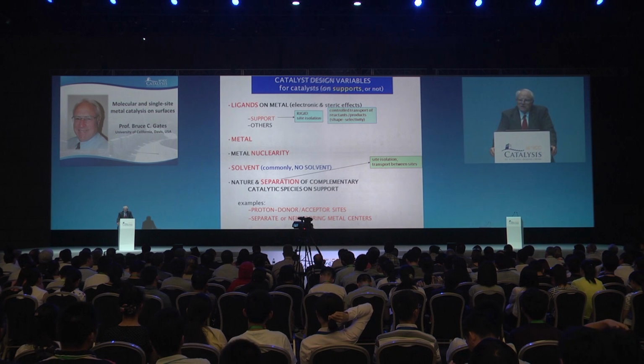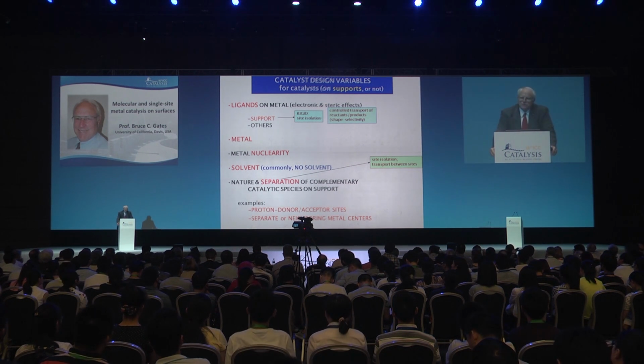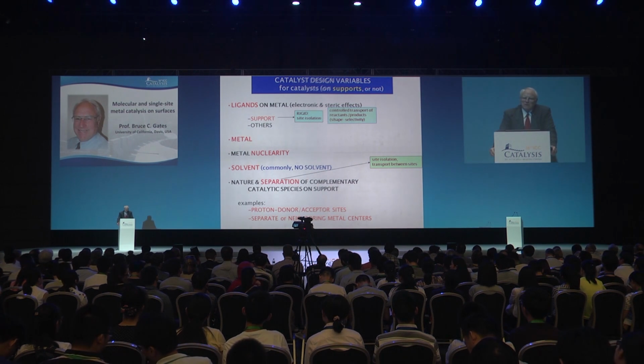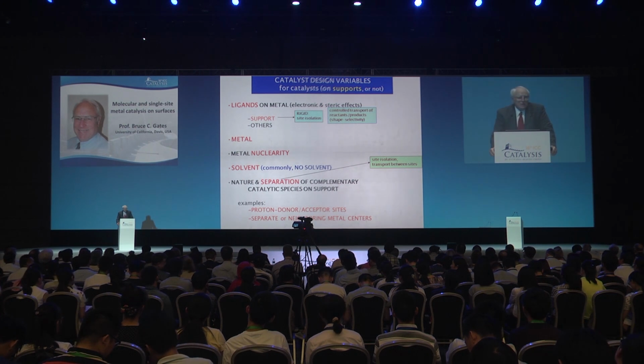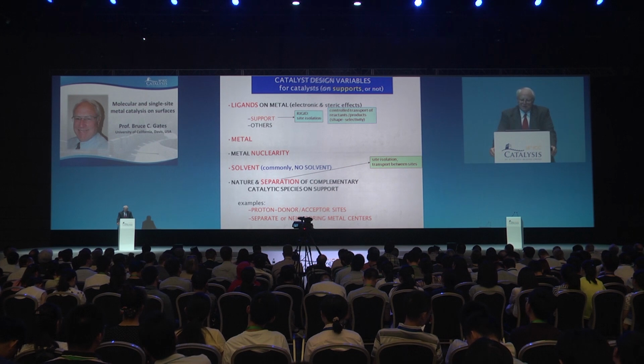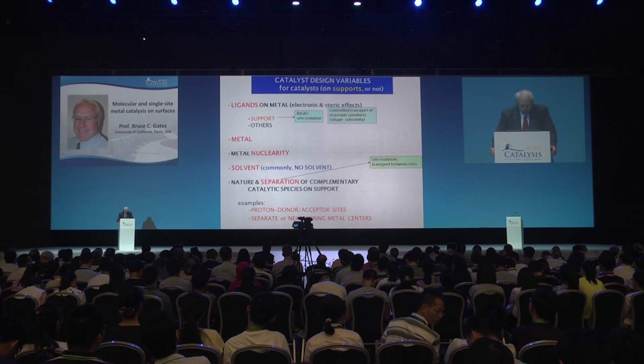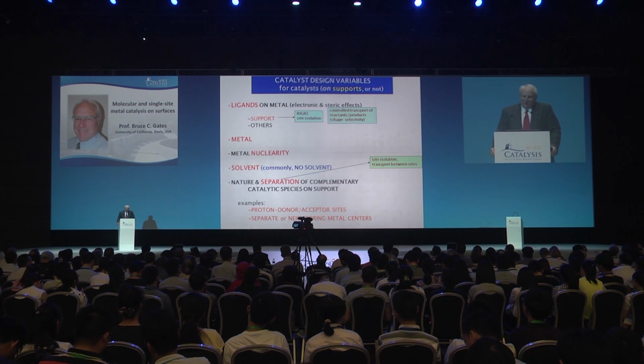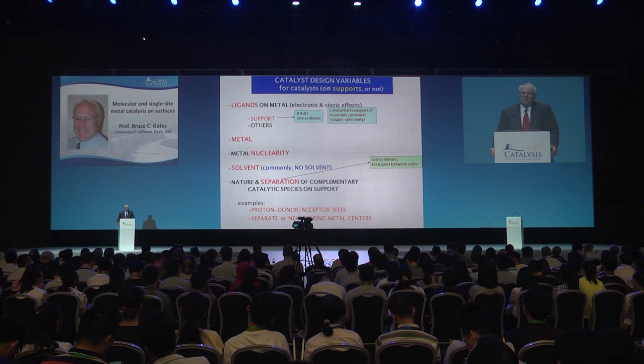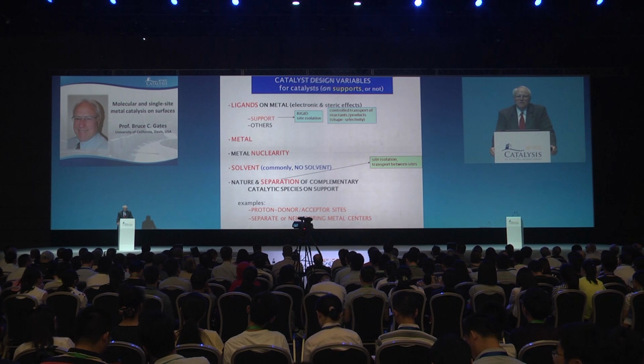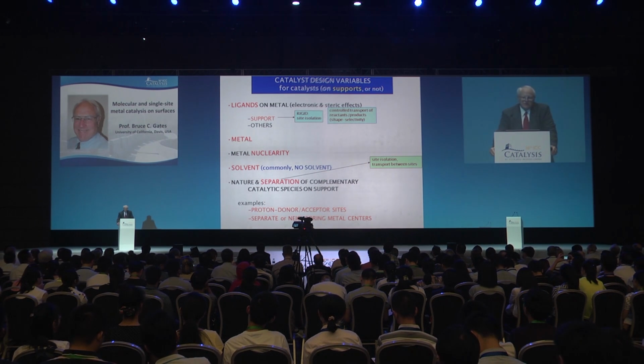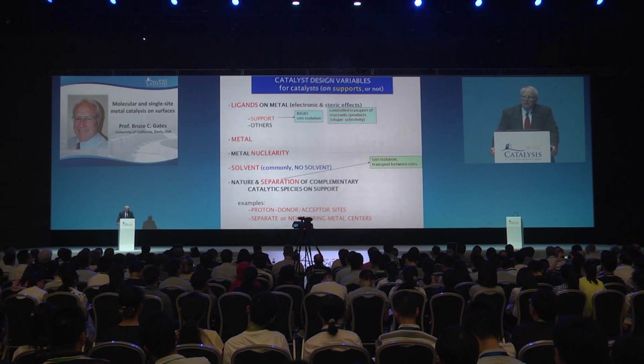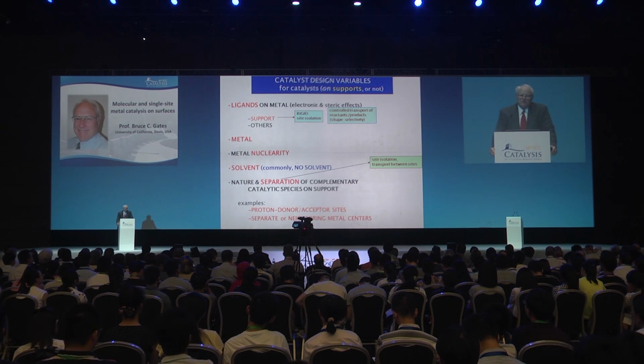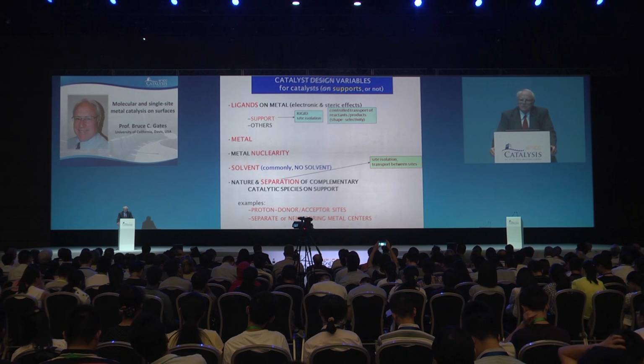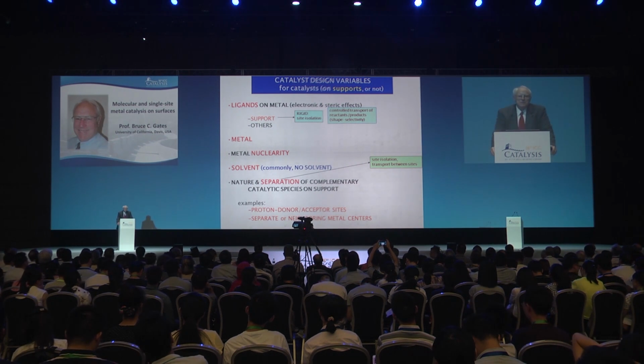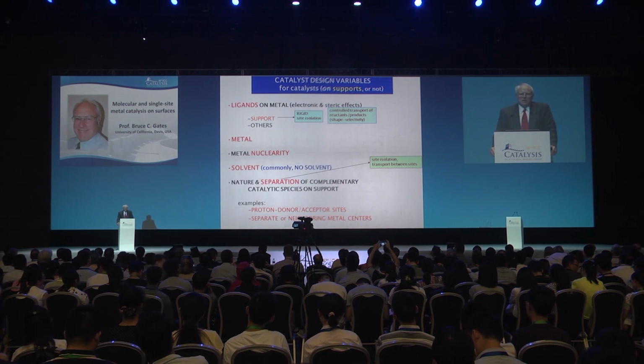And here's where there's an interesting distinction between homogeneous catalysis and surface catalysis. There's not much going on with metal clusters as catalysts in solution. They are often not stable, they're not easy to make, or not easy to make in high yields. But in contrast, we surface catalysis people usually have the metal in the form of polynuclear species, clusters. So there's big opportunity here to look at the zone, which I illustrated with the rhodium and with the gold, the zone between particles or small clusters, the ones more typically investigated in catalysis, and the mononuclear species. The very smallest clusters, not so easy to make, not so easy to characterize, can offer entirely new catalytic properties.